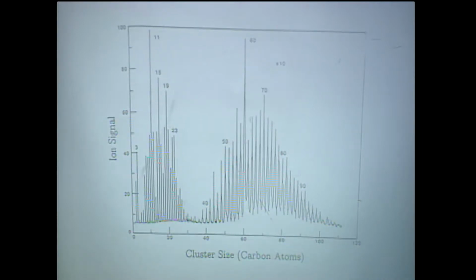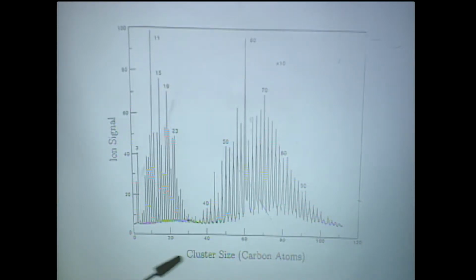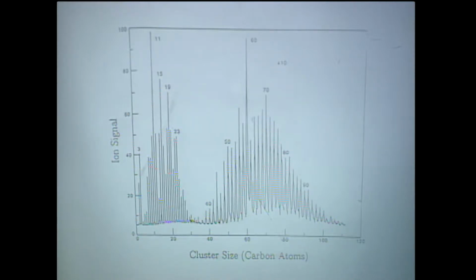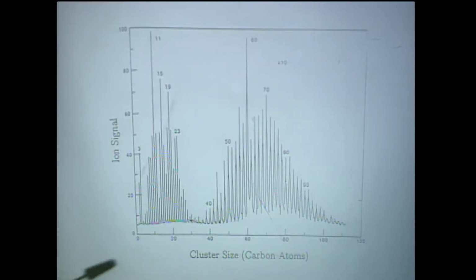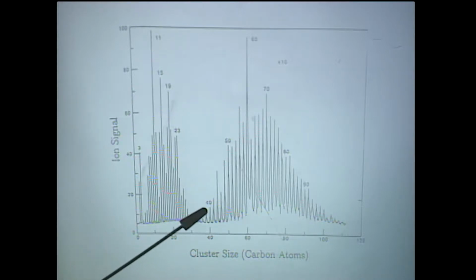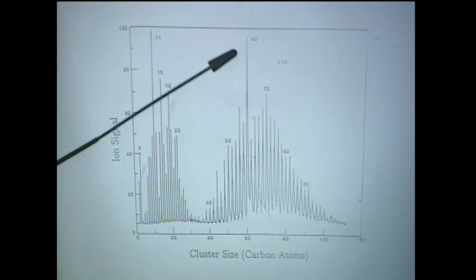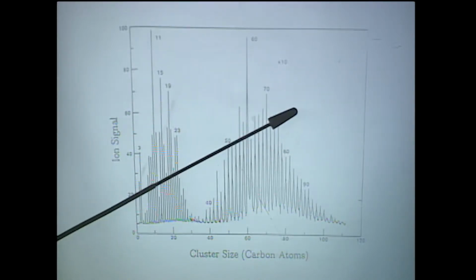Well, they pursued this work, whether it was because of our work or because of other people's work, because, as you know, in science, many things come together all at once. And they had the courage to go and look for what happened at these higher mass units. Here we see a plot of the number of species of a given type that are found, and on the x-axis, how many carbon atoms are contained therein. You could see that there's a new series that starts up somewhere close to 40 carbon atoms. And in this series, each peak is separated from each other peak by two carbon atoms. So that's a sign of what we were talking about. And there's a very large peak, much larger than its neighbors, around C60,